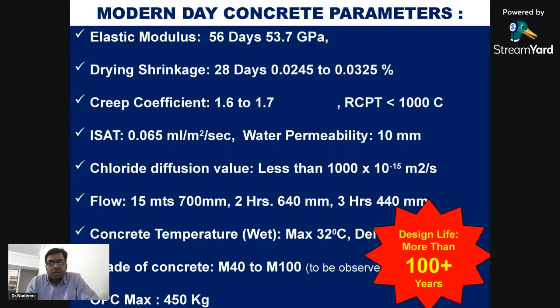Temperature, of course, at the time of pouring we are looking for less than 30 or 32 degrees centigrade, and the grade of concrete is in the range of this. OPC content, or pure cement content, is being restricted to 450 kg. All the specifications are going towards achieving a design life or service life of more than 100 years. So these are the specifications nowadays being specified in the majority of structures or concrete to achieve that kind of serviceability, service life or design life of concrete.